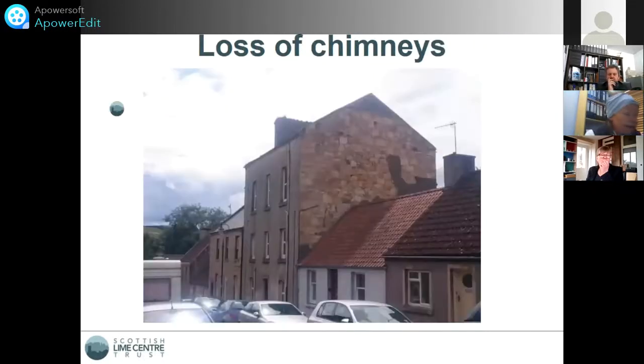And we've got issues of, and Stacey showed a very good example of the loss of chimneys and chimney stacks. And here we see an example of a gable end, where the chimney actually collapsed partially. It previously had a coating of cement harling over it, as you can see here, which has also come away. And because of the traits of cement, renders and harling are such that they will very often debond from a solid natural sandstone wall, it means that water gets trapped behind it.